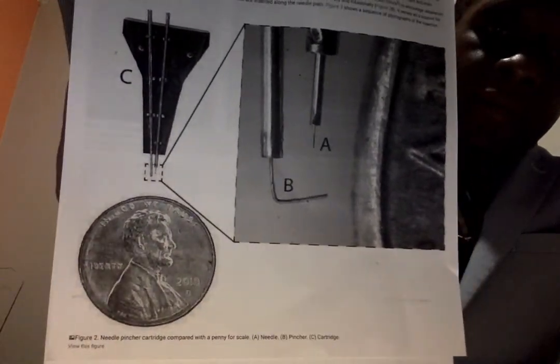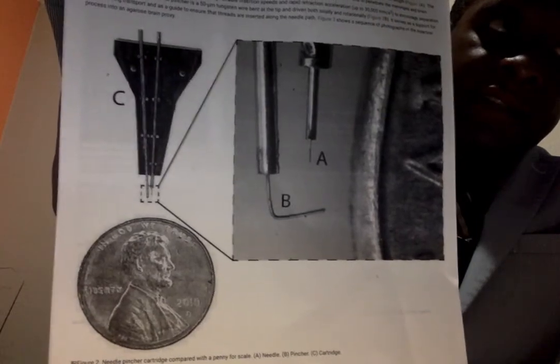Figures 2 and 3A. The needle, the relative sizes, well, not to scale, but relative sizes. The needle is milled from 40 micrometer diameter tungsten rhenium wire stock electrochemically etched to 24 micrometer diameter along the inserted length, figure 2A. The tip of the needle is designed both to hook onto insertion loops for transporting and inserting individual threads, and to penetrate the meninges and brain tissue.